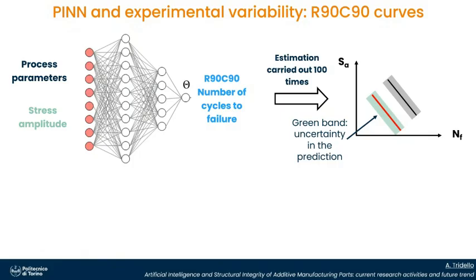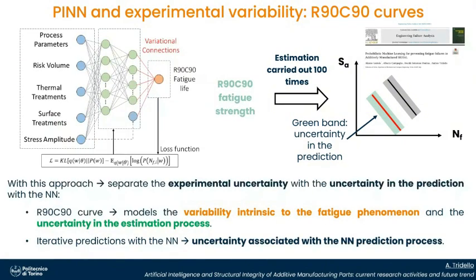So this is the neural network. We have the process parameter and the stress amplitude, and then we add the R90C90. We have in output the R90C90 number of cycles to failure, but we exploit the characteristic of the Bayesian neural network. We obtain non-deterministic prediction. So we repeat the prediction many times, and we obtain a green band which represents the uncertainty in the prediction. So to conclude with this approach, we can separate the experimental uncertainty from the uncertainty in the prediction.